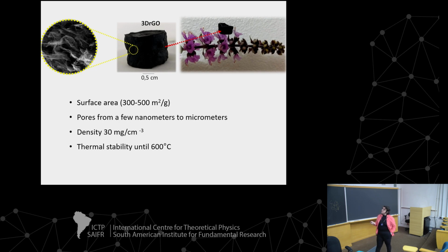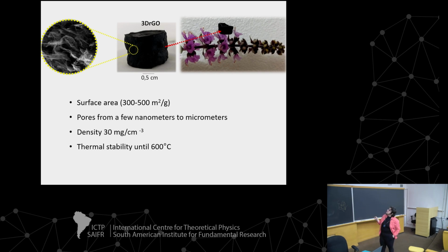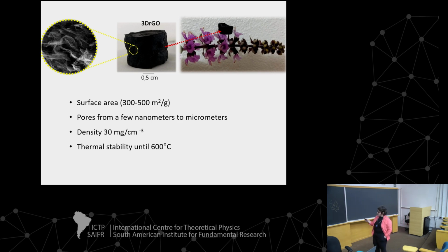These materials present a high surface area, pores from a few nanometers to micrometers, and low density. To see this, we have here a flower of basil. It's a tiny flower. We have our dried material inside this flower, and the flower remains intact. It's such a low density material. And these materials present a thermal stability up to 600 degrees Celsius, which is very high.